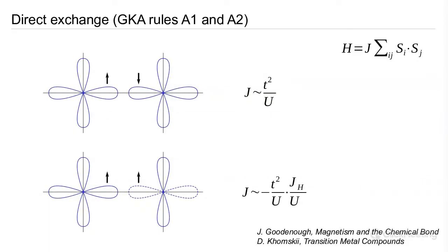So if we have direct exchange, let's imagine here we have two d orbitals that are singly occupied, and they overlap with each other. Then the Pauli exclusion principle from this hybridization requires that these two spins are anti-parallel in the ground state. So here we get an effective antiferromagnetic exchange interaction, and J can be written to reasonable approximation as t squared on U, where t is some measure of the ability of the electrons to hop between the two sites. This is the measure of the degree of orbital overlap, and U is the Coulomb repulsion that we'll be familiar with.